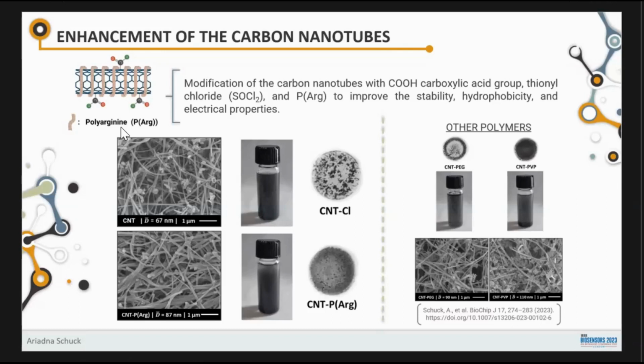And then after that, I coated the carbon nanotubes with polyarginine. And just to compare the improvement of the uniformity here, you can see the raw carbon nanotubes compared with the other polymers that I treated, also polyethylene glycol and PVP. PVP had a good response on the uniformity, but the conductivity decreased too much with the PVP presence around the carbon nanotubes. So polyarginine was the one that didn't affect the conductivity that much and also improved the uniformity of the surface, and it also reduced the defects. You can see there are many nodes here in the doped carbon nanotubes, but for the polyarginine one, you can see fewer nodes. And the diameter increase was around 87 nanometers compared to the 67 nanometers for the carbon nanotubes.